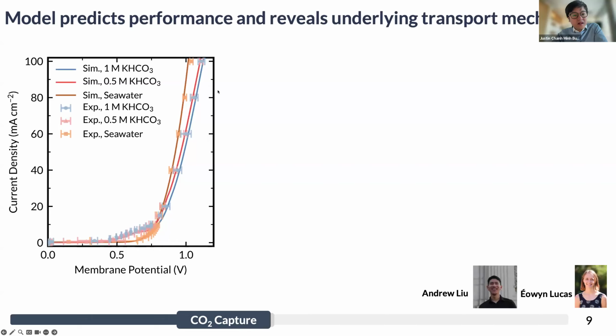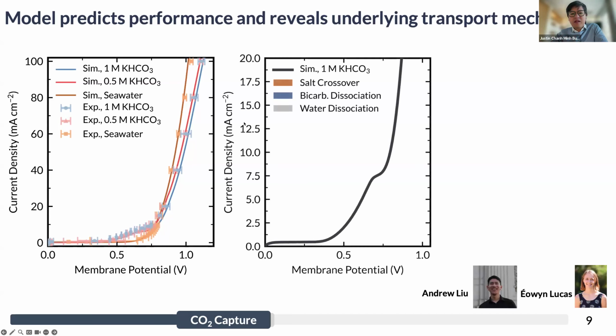And sort of the magical thing is you can see here that there's these very non-intuitive behaviors to these polarization curves. Typically, when we're running a bipolar membrane, we expect a very typical exponential takeoff on these curves. But what we see is these very interesting sort of hump behavior at about half a volt of applied potential across the membrane. So something that was really interesting, but it's also something that both the experiment and the model reproduce very faithfully, which to us was a pretty good sign that the physics of our model were representative of what was happening in Éowyn's experiments with these membranes.